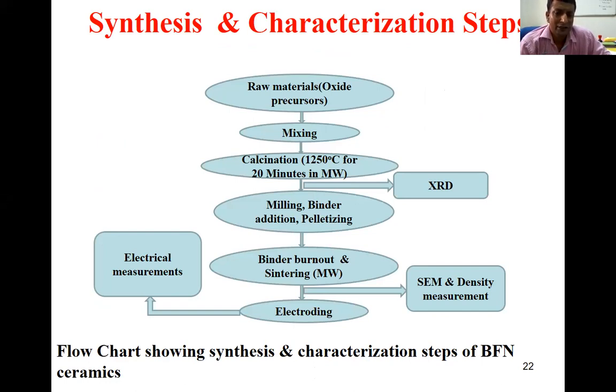Now in the case of this BFN system, we have done the calcination at 1250 degrees Celsius for 20 minutes. Let me highlight here that the main characteristic is that, since the heating mechanism is totally different, the heating temperatures and the time durations are very less in microwave heating compared to conventional heating. But here we chose this 1250 degrees Celsius.